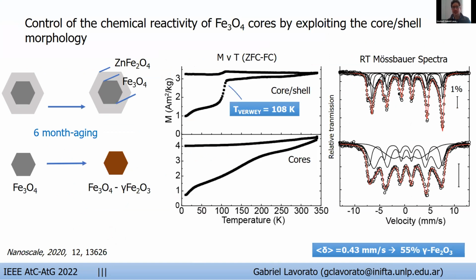So we noted that after these 6 months, the magnetization temperature curves still exhibit a clear Verwey transition for the core shell sample, which means that we have stoichiometric magnetite in this sample, while the average isomeric shift of the Mössbauer spectra of the aged cores indicates that in this case we have 55% of maghemite.